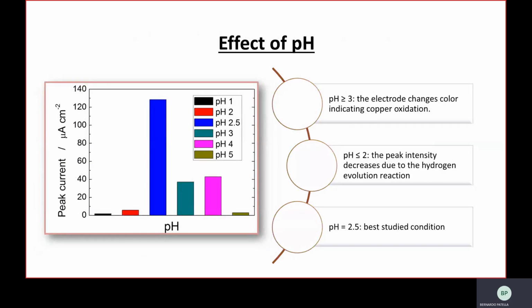Finally, the effect of testing pH was studied by measuring the peak intensity of 1 millimolar nitrate at different pH. The results show a big effect of this parameter. Indeed, using pH higher than 3, the electrode starts to oxidize to copper oxide, so reducing the signal intensity. While using more acidic pH, the peak intensity decreased due to the hydrogen evolution reaction. The best result was found using a pH of 2.5.